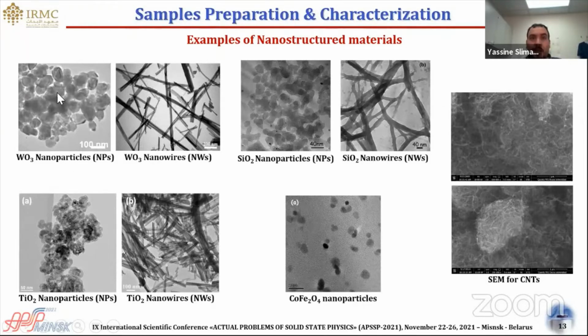For example, here it is about 100 nanometer for tungsten oxides, 20 nanometer for the magnetic nanoparticles, and 30 to 40 nanometer for the case of silica and titanium oxide.